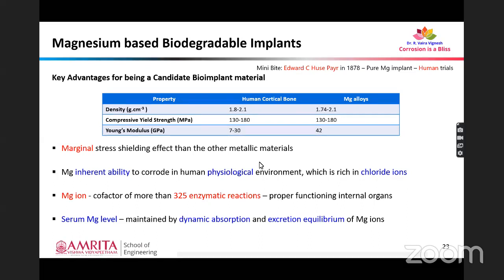Added to that, if we use these magnesium alloys, that will result in marginal stress shielding effect compared to any other metallic materials. Added to that, magnesium has inherent ability to corrode in the human physiological environment, which is rich in chloride ions. And magnesium ion is one of the cofactors of more than 325 enzymatic reactions that are required for proper functioning of internal organs. Besides, the serum magnesium level is maintained by dynamic absorption and excretion equilibrium of magnesium ions. So this makes magnesium one of the candidate materials for biodegradable implants.